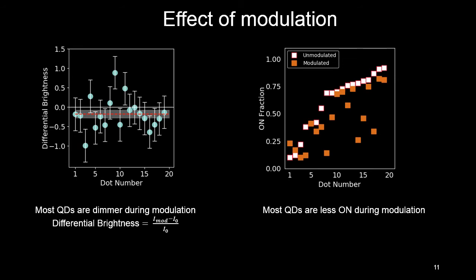The other thing we did is check the on fraction of the dots, which is not quite the same thing. This is the amount of time that the dot is on referenced to the total duration of the experiment. The white squares show the amount of time the dot was on when I'm not modulating, and the brown squares show the amount of time the dot was on when I am modulating. You can see that in almost all cases the dot was off more when I had the modulation laser on, and so this was a hint to us that something really was happening and was worth analyzing more carefully.